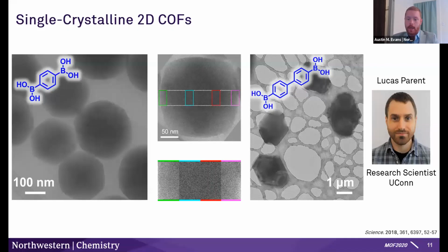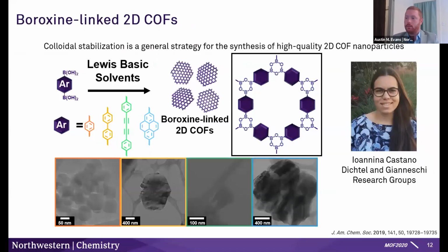And we found quickly after that that this strategy seems to work for, one, a lot of boronate ester-based 2D COFs, but also seems to work for other families of BO type chemistries. So this is a boroxine, it's a 6-member BO linkage. And essentially the same strategies we use to form boronate esters seem to generalize here as well.